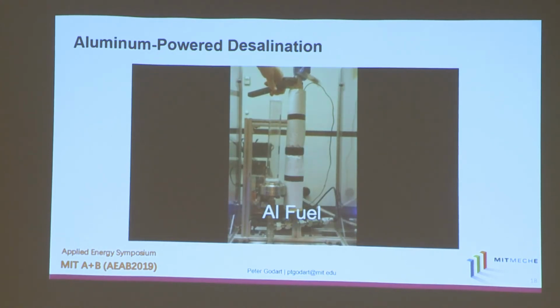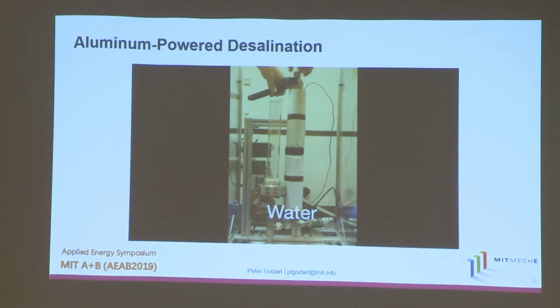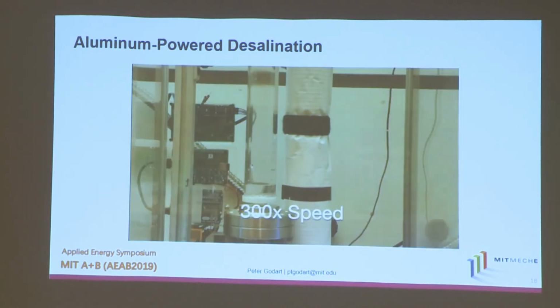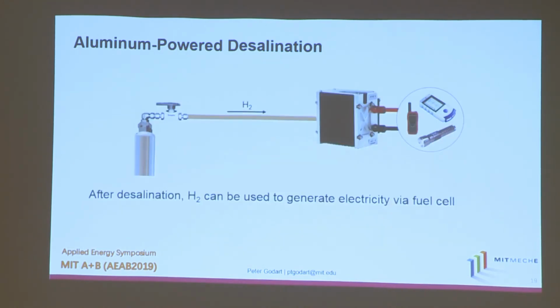Now we can also generate clean water using the thermal energy that's output. So here's a system that we developed where you just dump the aluminum fuel and some water in an enclosed cylinder that contains some seawater. As that reaction occurs, we develop high pressures which can push that seawater through a semi-permeable membrane to separate water out via reverse osmosis. And then in this type of system, the hydrogen is simply a working fluid, and it's not consumed in this process, so we can then use that hydrogen to generate electricity later in a fuel cell.